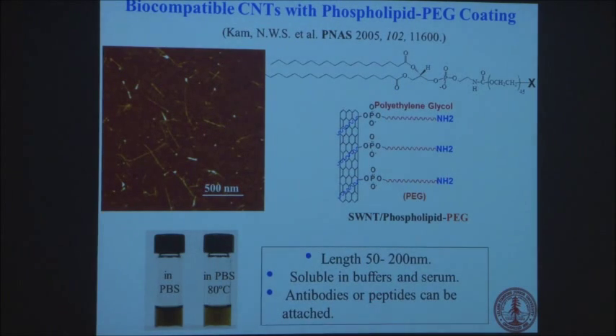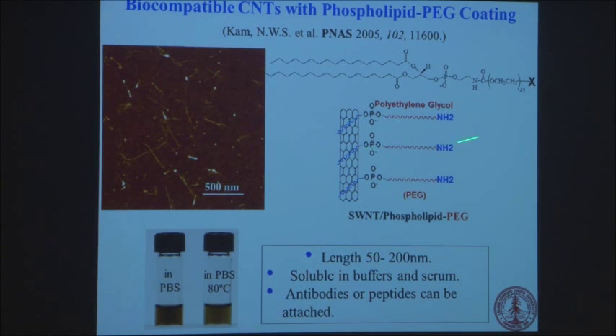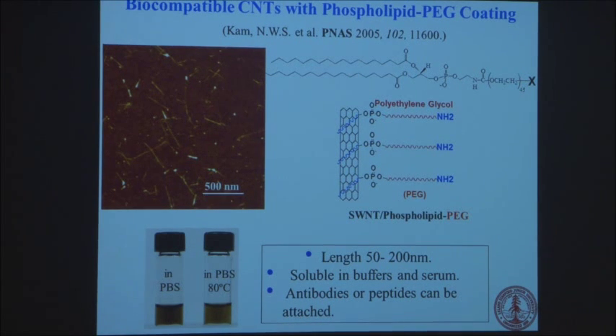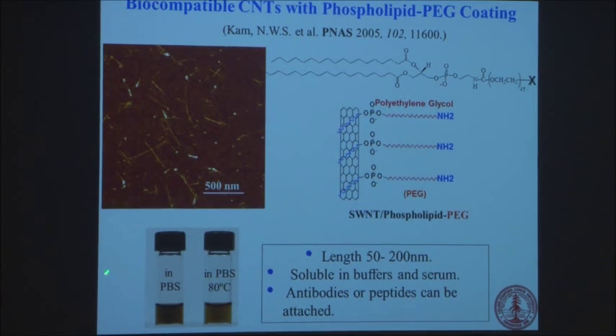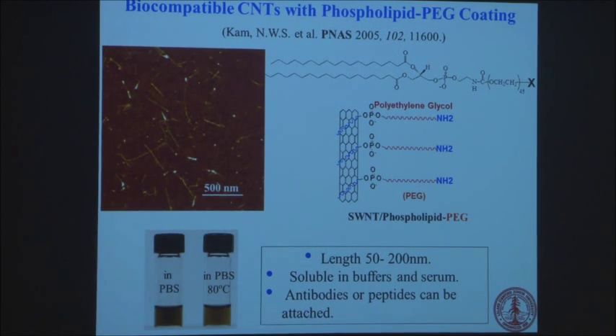In order to make these things useful for biological imaging, you have to make them water soluble. Here I'm showing you one way we can coat these nanotubes with a surfactant molecule so that they are hydrophilic and can go into water. You see, this is really a nice solution of these nanotubes.